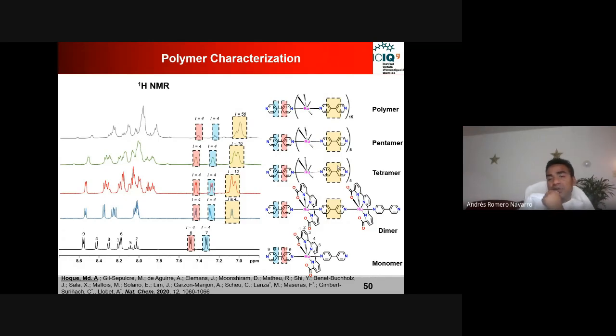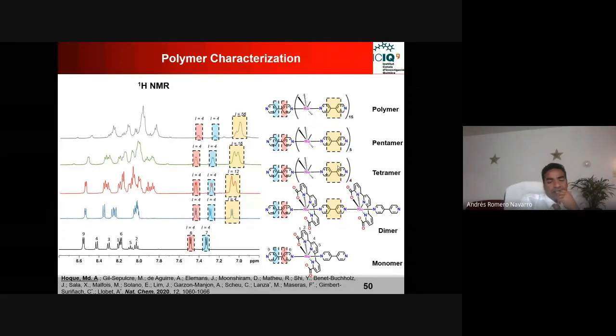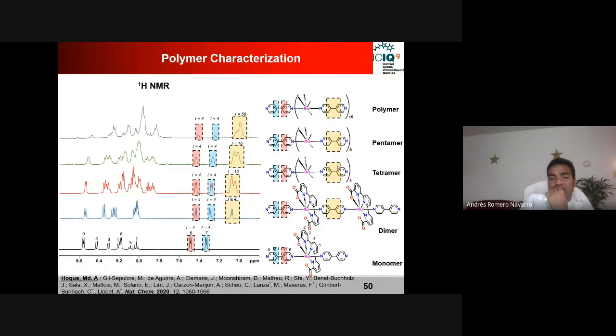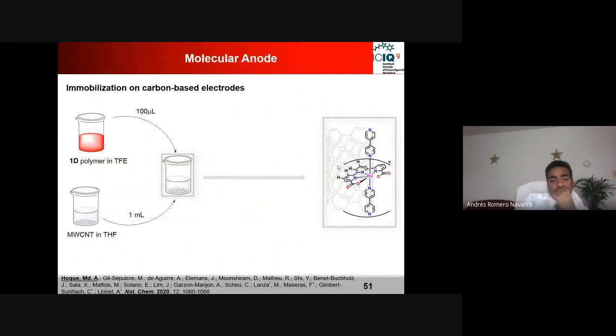And then our purpose was to design this anode material, right? So we want to put those on the surface. So how can we do that? First we thought, okay, we want to put those molecules onto some solid surface. One of the solid surfaces that we are using is the carbon nanotube. I showed in the introduction that people have tried that for the pi-pi stacking. So I took a little bit of this polymeric compound and put it into a suspension of this multi-wall carbon nanotube. So this is the structure of this multi-wall carbon nanotube.